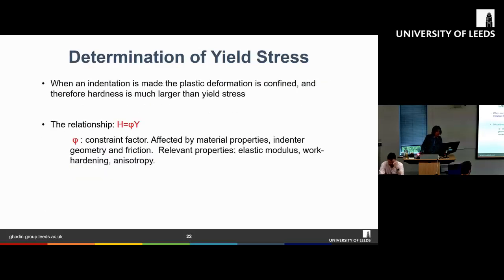Yield stress. When an indentation is made, plastic deformation is confined. Therefore hardness is much larger than the yield stress itself. The relationship between yield stress and hardness can be governed by a simple equation here. Hardness is simply a function of the yield stress times the constraint factor.